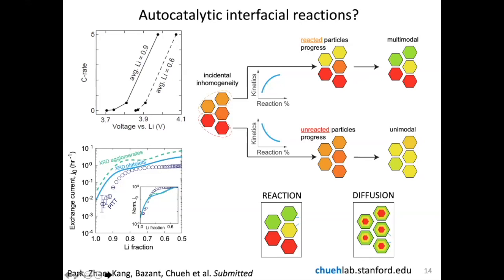So why does this happen only on reaction limitation and not on diffusion limitation? It's actually very simple. When you have a reaction-limited intercalation, the particles themselves have a relatively homogeneous composition profile. So that means the surface composition and the bulk composition are similar. And as you remove lithium, the composition on the surface changes. But when you have diffusion limitation, the surface of the particle remains almost in the fully delithiated state on charging due to the diffusion front. So from the perspective of the electrochemistry, although the particle lithium content is different, the surface composition is actually the same. So this is what leads to equalizing the composition. So this is a very simple picture to understand why a reaction-driven process can control the growth and the retardation of heterogeneity in the layered oxide cathodes.